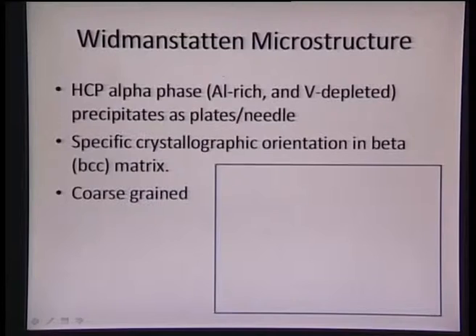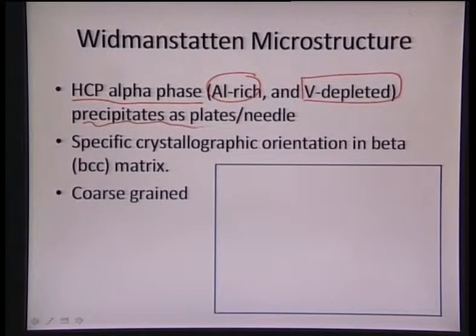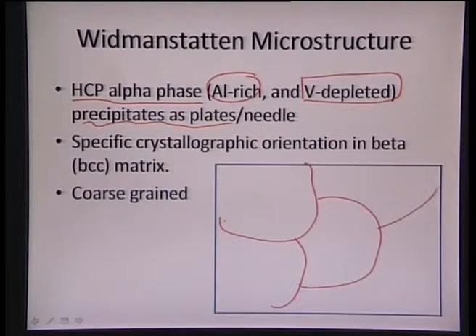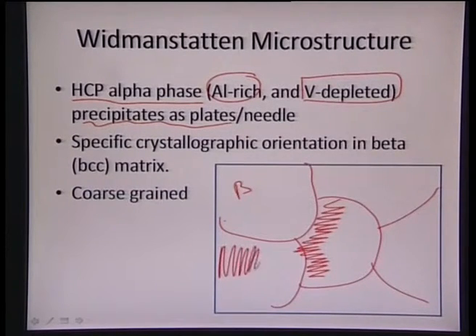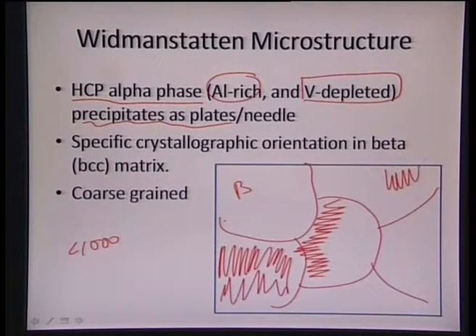So we can see this Widmanstätten structure. Basically we see the HCP alpha phase, which is aluminum rich and depleted in the vanadium part, starting to precipitate as a plate or needle. So we see that we had grains like this for the beta, and then within that we see the nucleation of this alpha phase, which can start nucleating within like this, and then we have this beta phase, and then again we will see alpha phase nucleating, because alpha phase will be much more stable at less than 1000 degrees centigrade. We will see more of the grains which are forming alpha now.